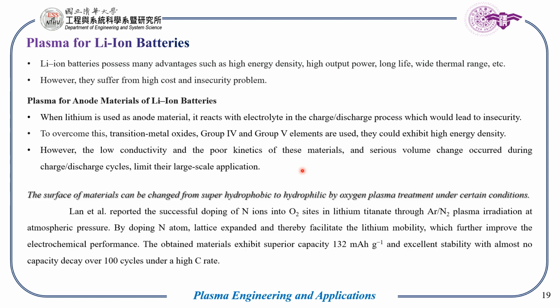So this can be solved by surface treatment of these materials using plasma technology, and the surface of the materials can be changed to super hydrophobic or hydrophilic by oxygen plasma treatment under certain conditions. For example, here we can see that researchers reported successful doping of nitrogen and oxygen-nitrogen ions into the oxygen sites in lithium titanate through argon-nitrogen plasma irradiation at atmospheric pressure. Further, by doping nitrogen atoms the lattice gets expanded, and thereby they facilitate lithium mobility. Further, they improve the electrochemical performance. The obtained materials also show a higher capacity of 132, which was earlier 100, and excellent stability with almost no capacity decay over 100 cycles.